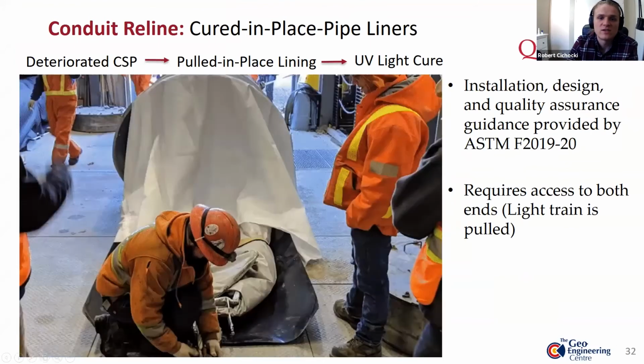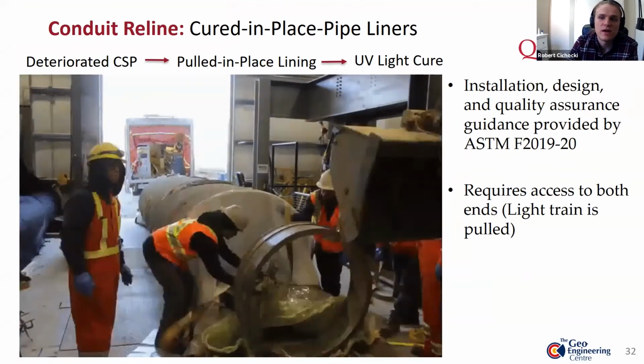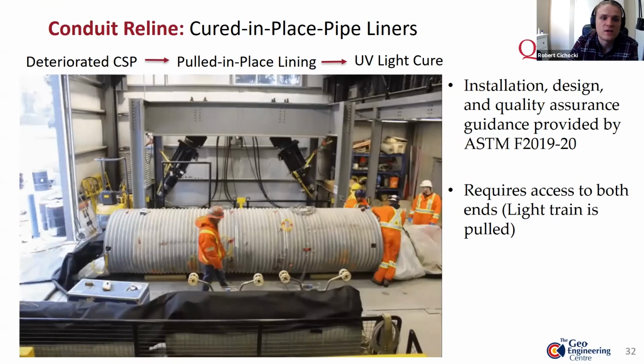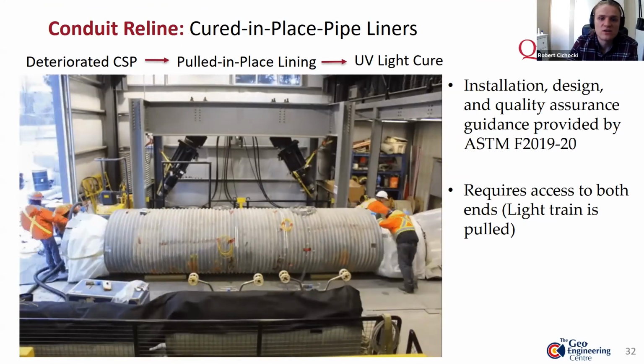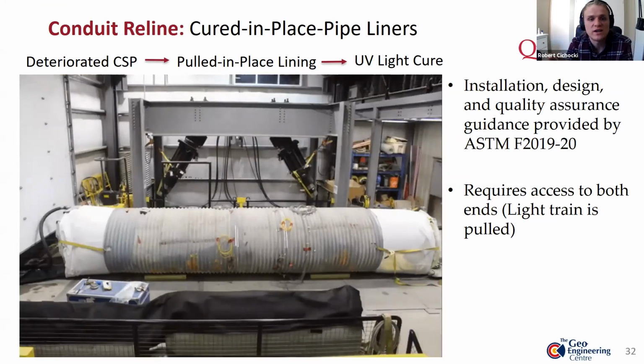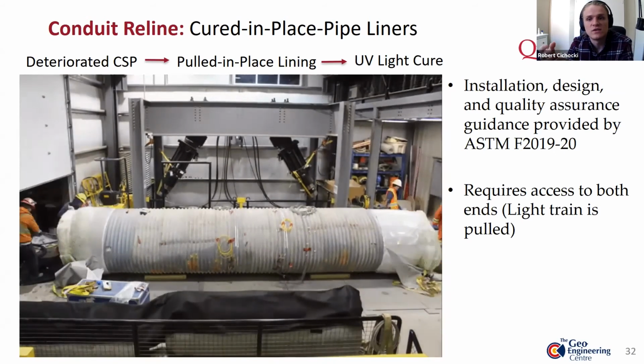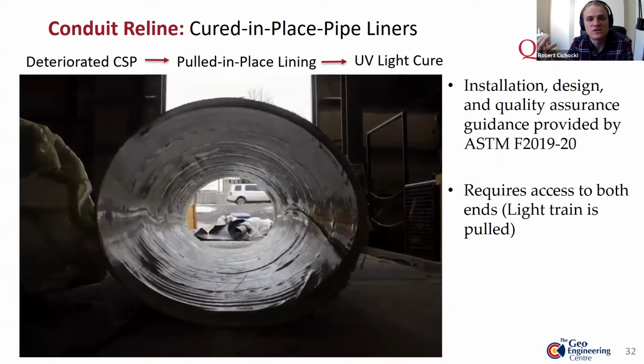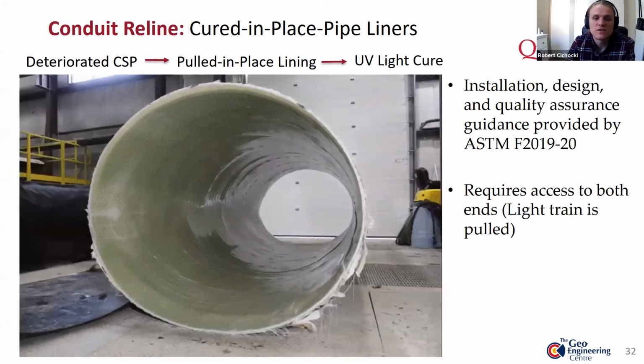Next, we can see a liner being installed using the pulled in place method and being cured with UV light. So with this installation, the liner is pulled into place while being dragged over a sliding sheet. Once it's in place, it's expanded with air pressure, and the UV light train is then inserted and the liner is cured. Guidance for the installation, design, and quality assurance for GFRP liners is provided by ASTM F2019.